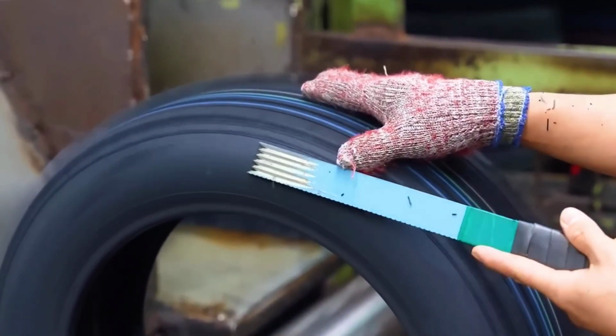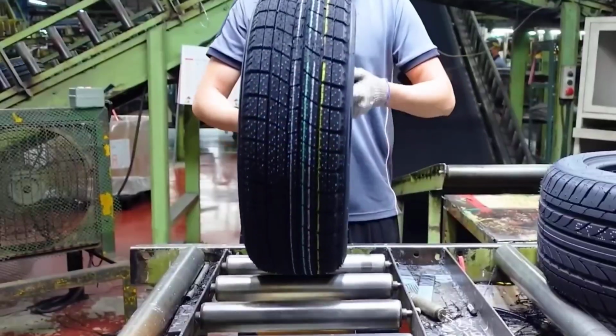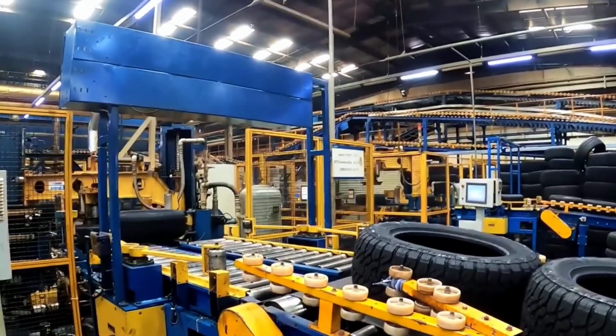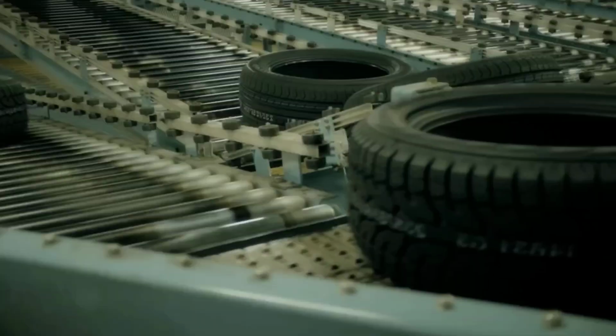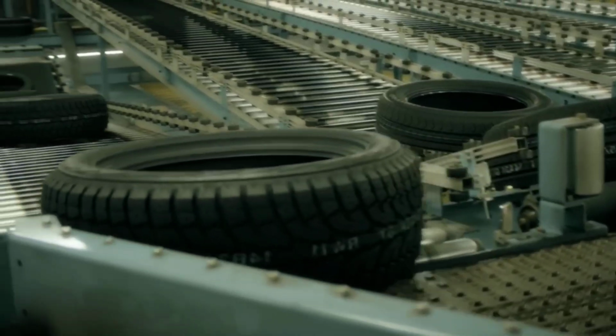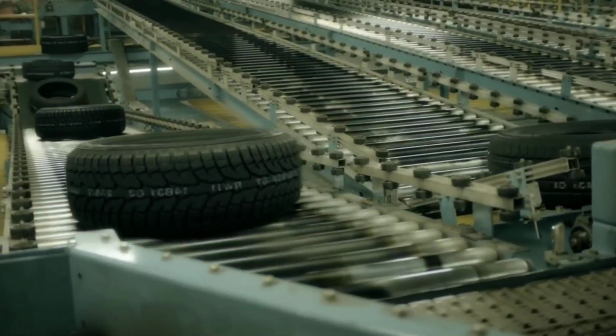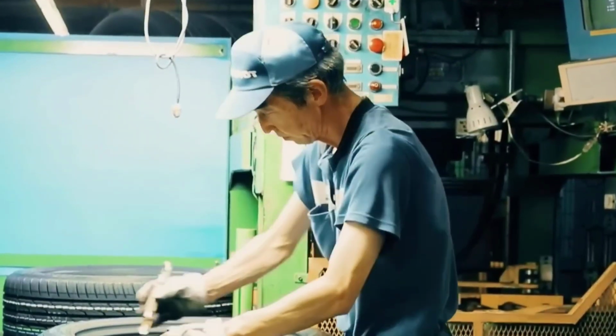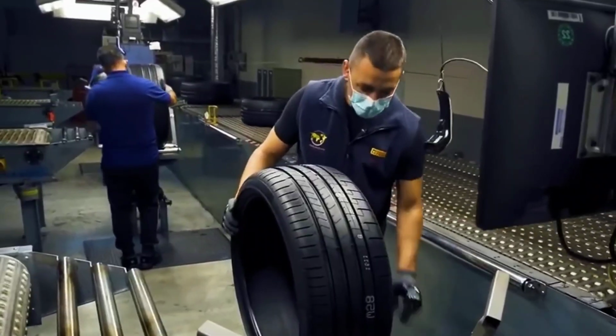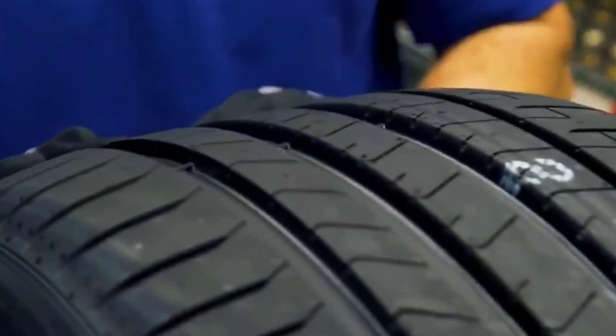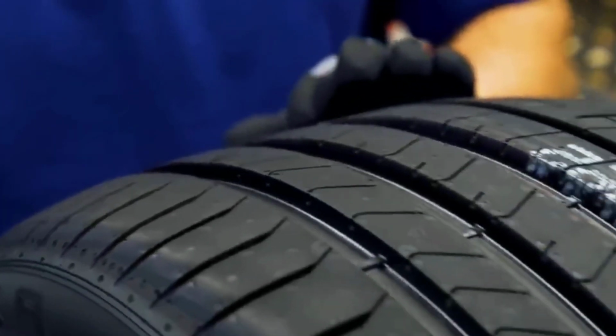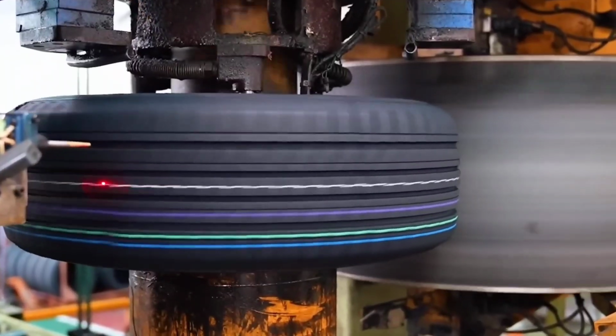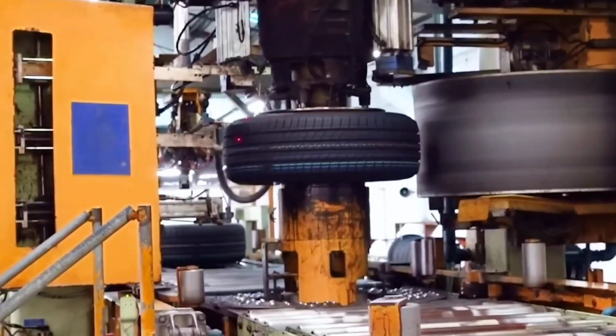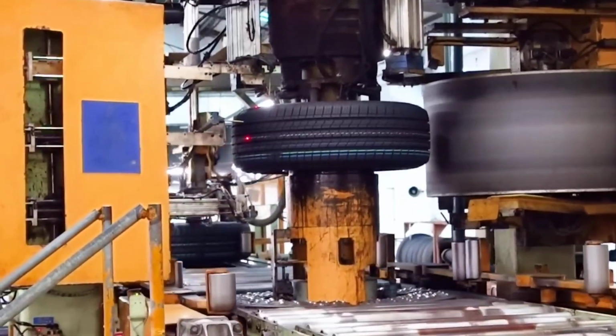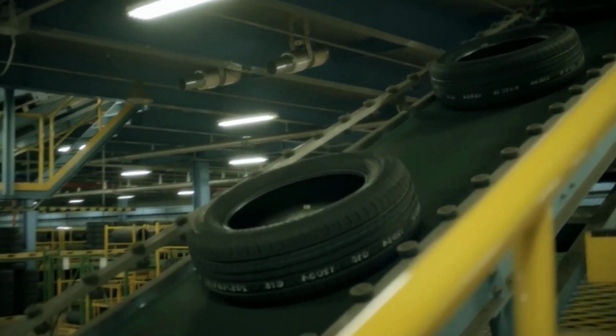Industrial laser beams scan the entire surface to check the tire's roundness, center alignment, and thickness. Even the slightest deviation is enough to disqualify it from moving forward. Next, the tire is mounted onto a rotating spindle and inflated with compressed air at a pressure higher than its normal operating level. This test checks for air retention and structural integrity under stress. Any leaks or abnormal deformation are instantly flagged by the system.